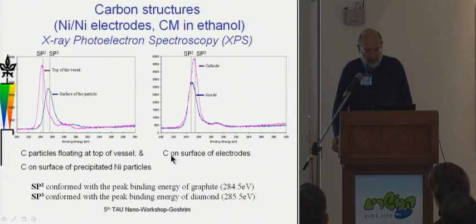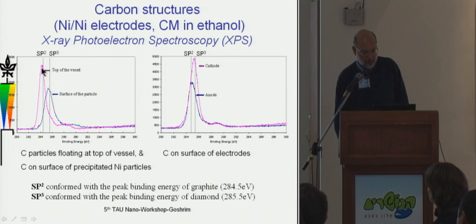The carbon that's collected from running contact mode arc between nickel electrodes in ethanol differs depending upon where you collect it. If we take some of these carbon particles that were floating near the top of the vessel and use XPS, we see that the binding energy seems to be typical of sp2 binding, graphite-like binding. And that's not a big surprise, because this is basically a graphite-like structure.